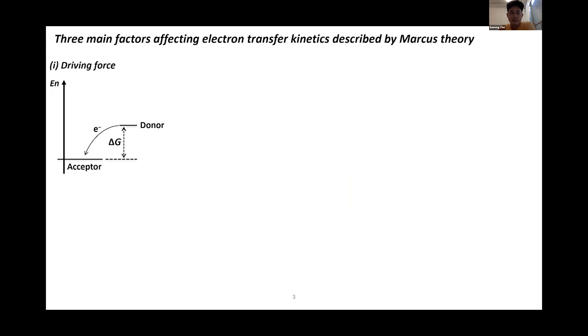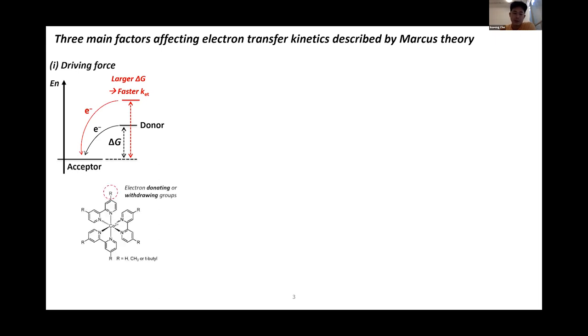So there are several factors significantly affecting these electron transfer kinetics, especially described by Marcus theory. I'll introduce three main factors. First is driving force, which means the energy difference between the donor and acceptor molecules. So if you increase the delta G, we can get fast charge transfer kinetics. And this can be done by changing the molecular structure of redox molecules by substituting some motifs with different inductive effects. However, increasing the delta G may often end up with potential energy loss. So one challenge is to get this fast electron transfer with minimized or low delta G change.